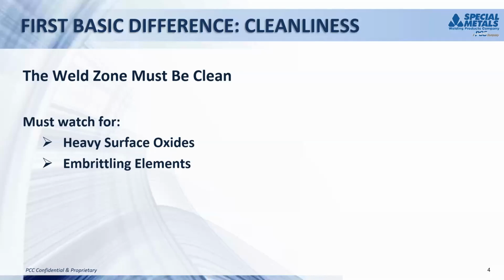But basically, we have to watch out for heavy surface oxides on plate. Nowadays, I don't think we get too many plates shipped from suppliers with a heavy hot rolled surface oxide. But if you do, that's one of the things we need to watch out for. It needs to be removed before you start welding. And the other one, we need to keep embrittling elements away, especially those that contain sulfur, phosphorus, and so forth. Next slide, John.